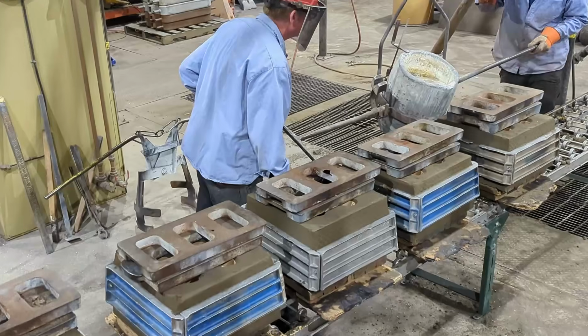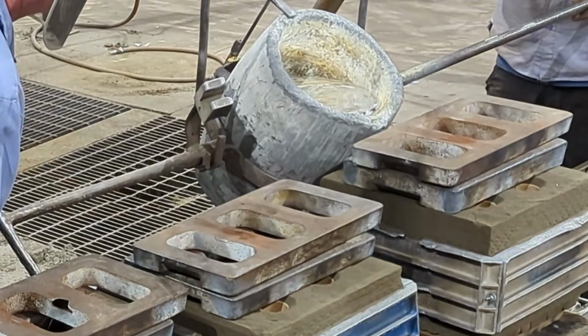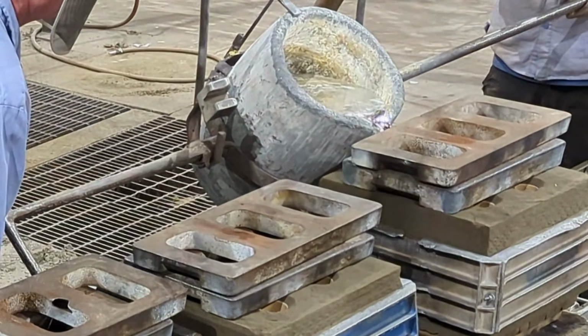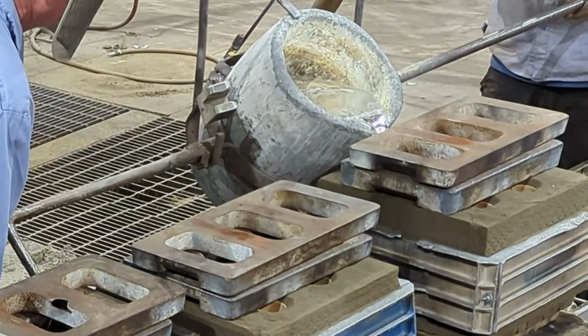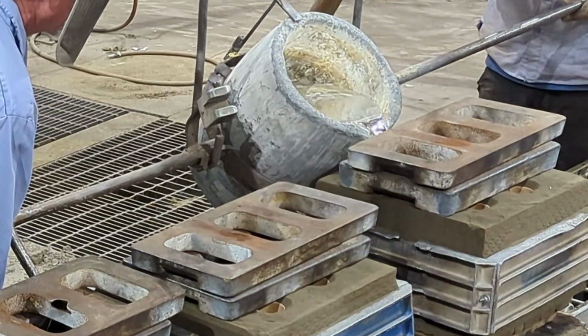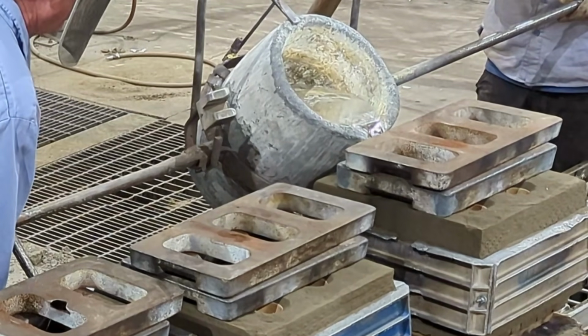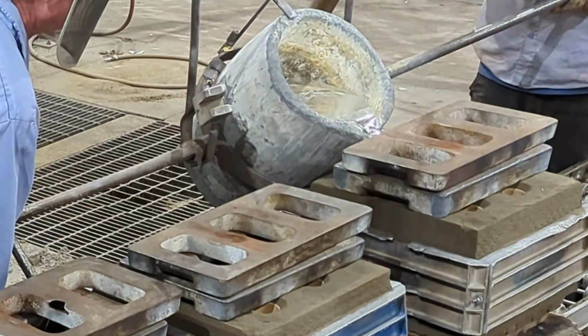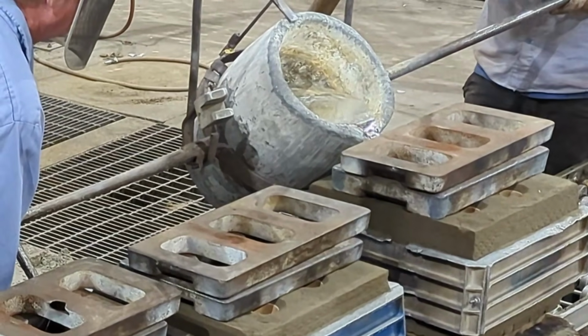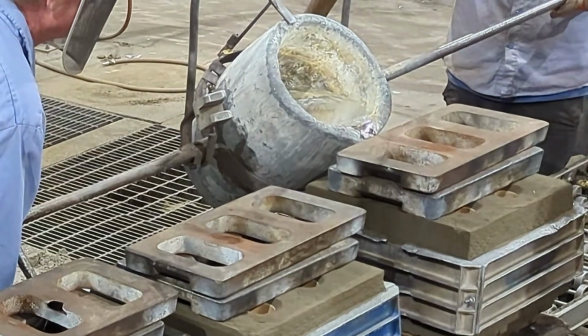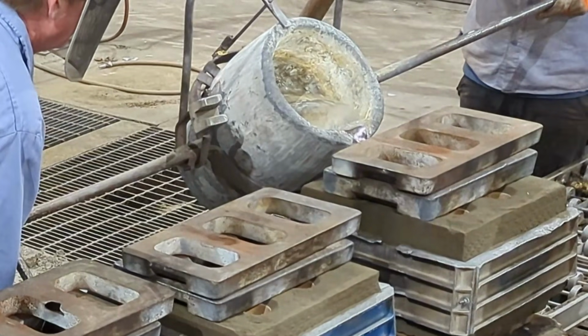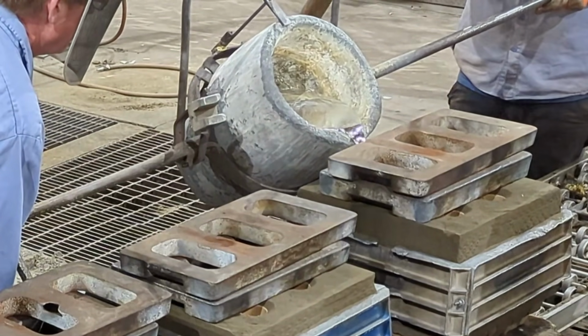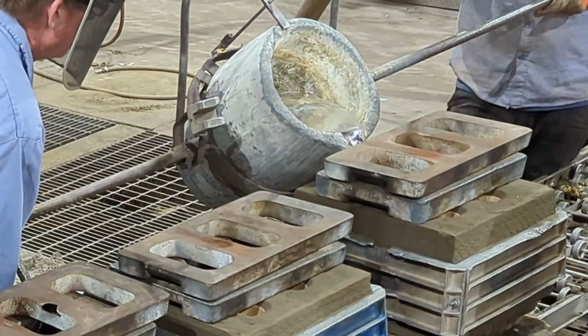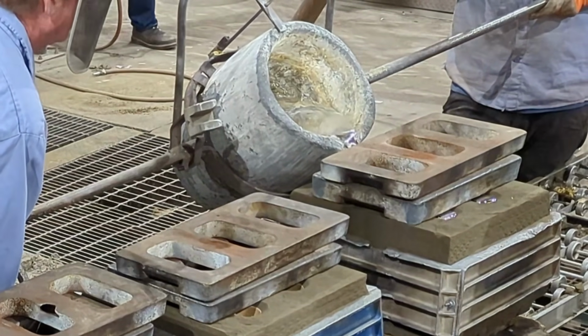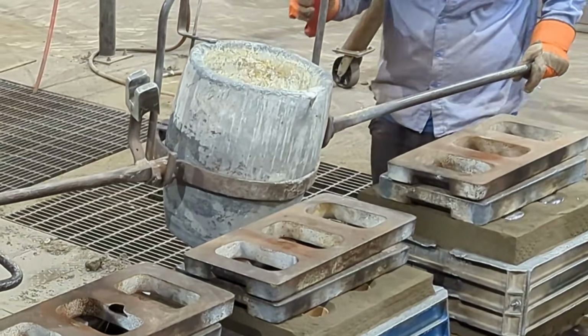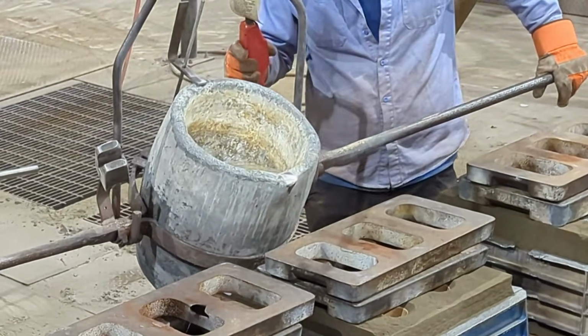Randy releases the tilt lock and slowly tips the crucible. Molten zinc flows down through the sprue, into the runners, through the gates, and begins filling each of the 6-part cavities. Within moments, you can see metal rising up through the thermal risers at the top. Here you can see the risers filling to the brim, a sign that the parts below are fully filled. They move down the line and pour each remaining mold.